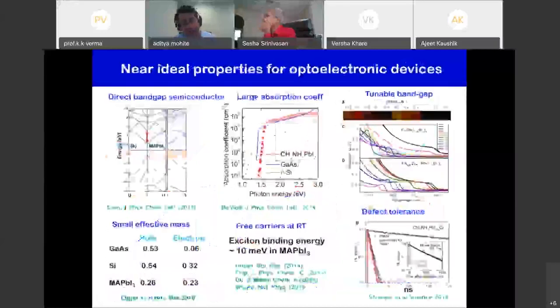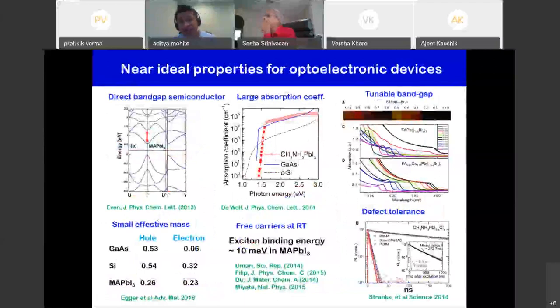In addition to these, there were a lot of other properties which are really ideal for making any type of minority carrier device or optoelectronic device. So let's walk through these. First, this is a direct band gap semiconductor, which means you have very nice conditions where light falls in. You can make a very thin layer of this material and absorb all the light, compared to silicon, where you need at least an order of magnitude more material. It has a very large absorption coefficient. The absorption coefficient is greater than 10 to the 5, which is comparable to that of gallium arsenide.